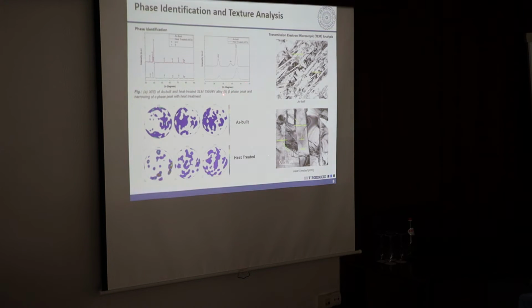And you see the peaks are wider in the as-built case. That means the solute present in the solvent is higher in concentration, and this shows the presence of martensite, which decomposes with the heat treatment. So the peak narrows down, and it's not clear there. You see it shows the 110 grain, and the beta grains are oriented towards the building direction.